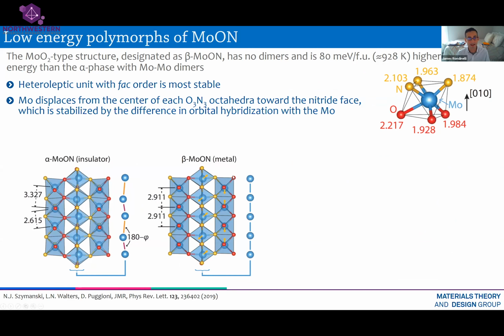So the high temperature phase, in analogy to what I described for vanadium dioxide, is the beta phase here for molybdenum oxynitride. In this case, the blue atom, which you see here, is the molybdenum atom. And in this beta phase, the moly atoms are all equidistant from each other. This is what we saw also in vanadium dioxide. And this structure is indeed metallic at the first principles level.